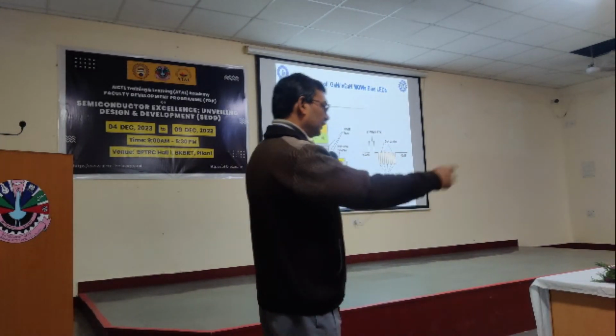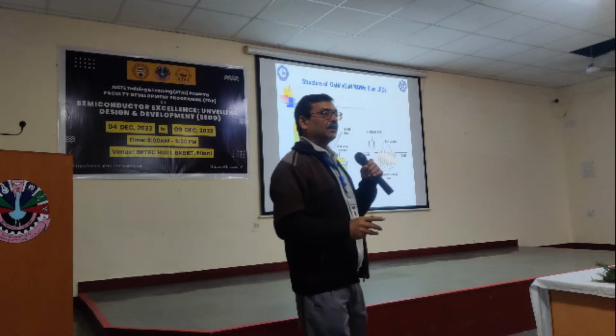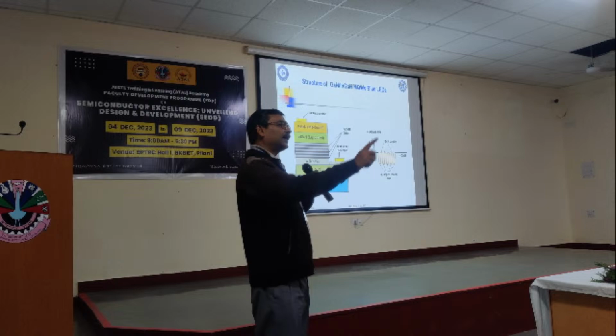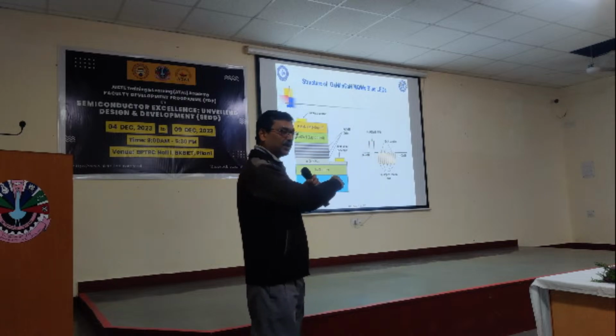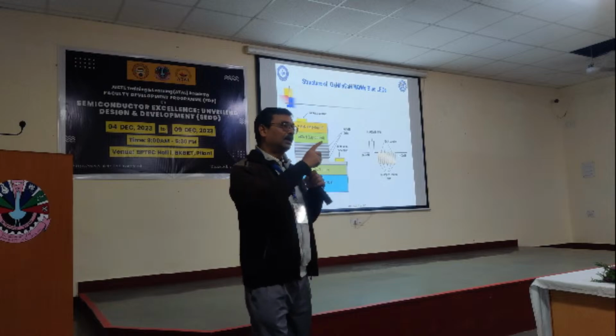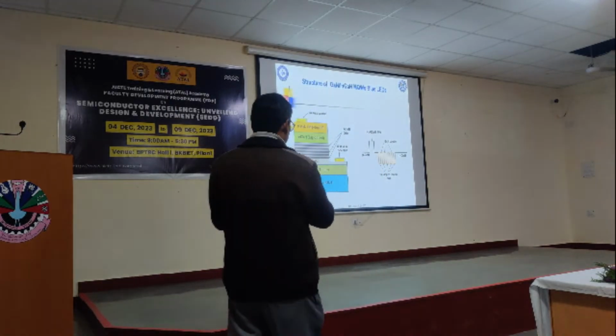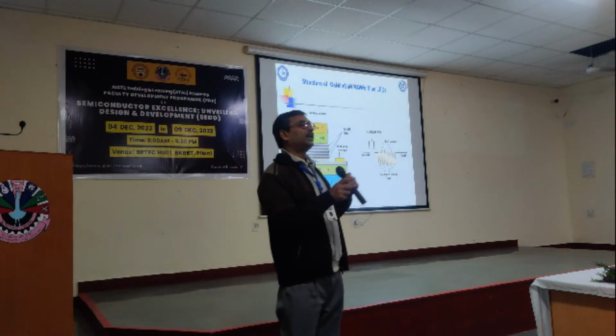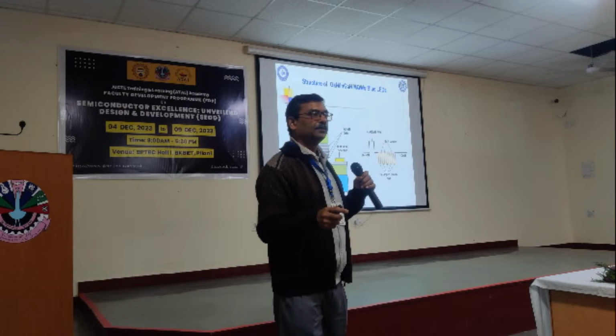But in other directions also we can grow the material. Depending on the growth of that material on other sides, we can have different planes of sapphire. Besides the C plane, another plane is the M plane, and another is the A plane. We use the C plane because in general, without any difficulty, we can grow that material. But the difficulty or the problem is there.